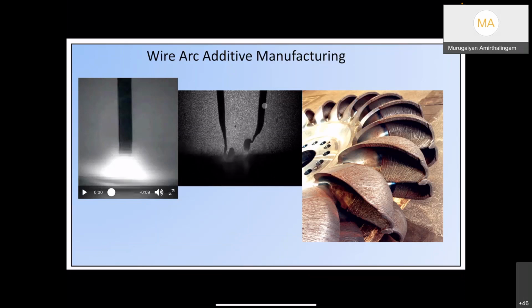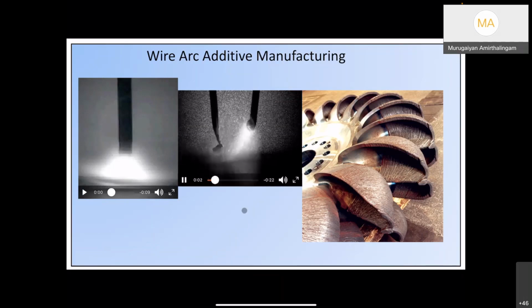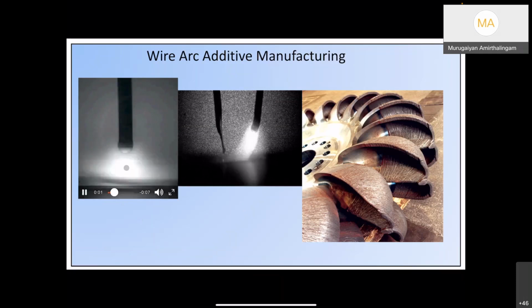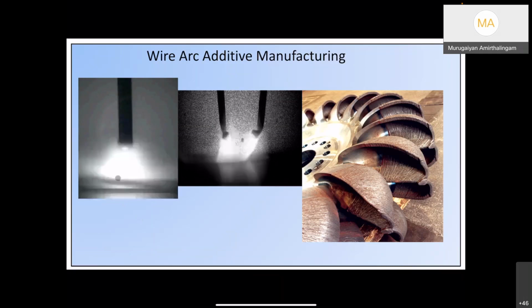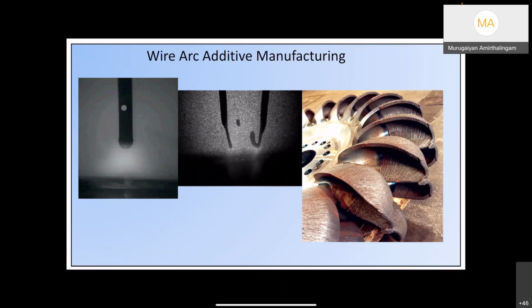So we have 2 wires simultaneously melted by the arc heat, and then the molten wire is deposited. When we use layer by layer deposition, we get a component build. And if you look at it over here, this is nothing but a welding process, right? So here we are using a single wire, where a single wire gas metal arc based process is used to create a molten pool, and then subsequently, if we build layer by layer, we get a component made. And since we use an arc as a heat source and a wire as a feedstock, this process is known as wire arc additive manufacturing.